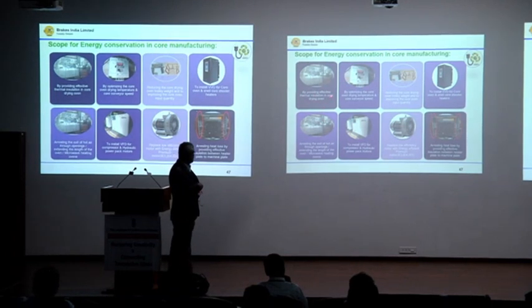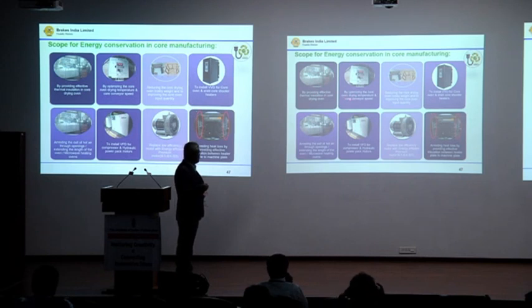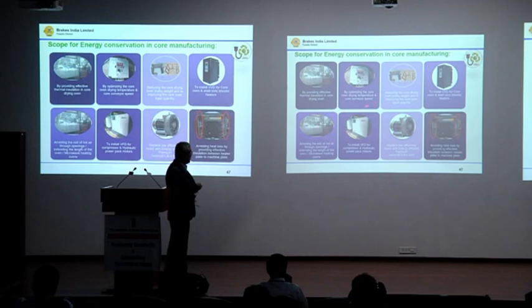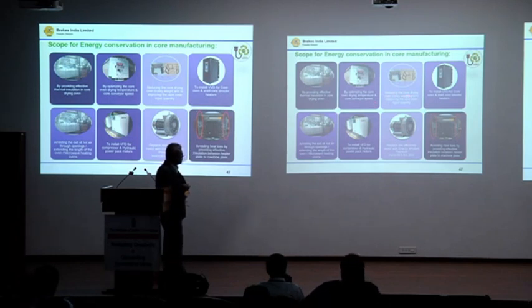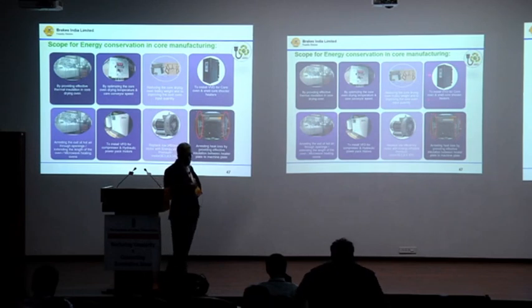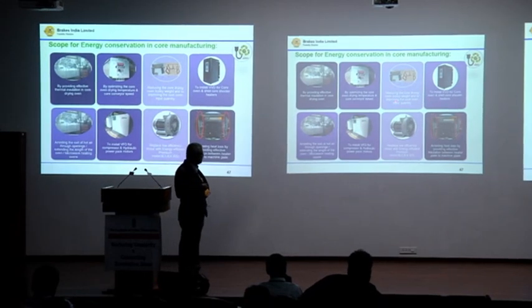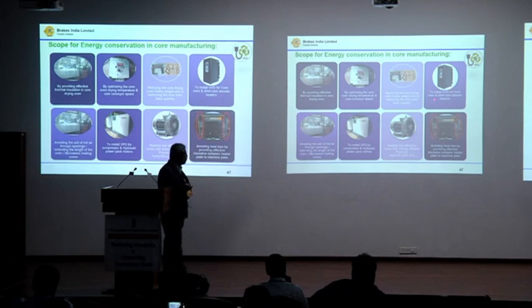Providing effective thermal insulation in the core drying ovens can reduce energy consumption drastically, by optimizing the core oven drying temperature and conveyor speed. By reducing the weight of the core trolleys in the oven, you can also reduce energy drastically. Here you can install VFD for core oven and shell core heaters.